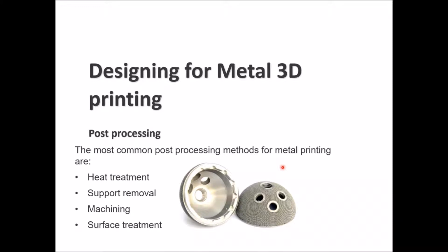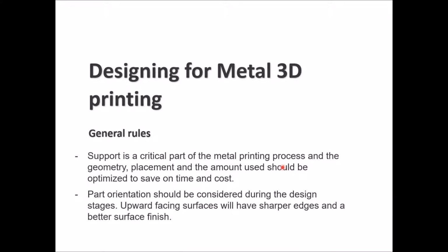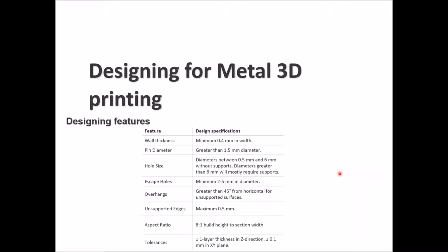Most common post-processing methods for metal printing are heat treatment, support removal, machining, and surface treatment. General rules for metal 3D printing: support is critical for the metal printing process, and the geometry, placement, and amount used should be optimized to save time and cost. Part orientation should be kept in mind during design stages. Upward facing surfaces are always sharper, having sharper edges and a better surface finish than the downward facing surfaces.